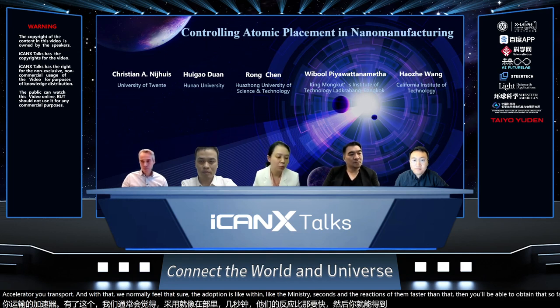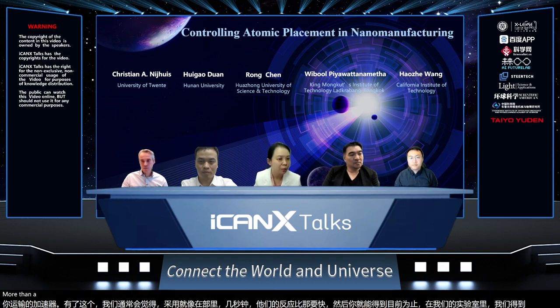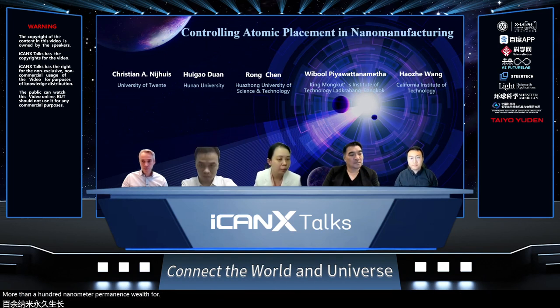In our lab, we obtain more than 100 nanometers per minute growth for the ALD process. That's pretty high, and that's the way we're trying to push to the limit. At the same time, in order to keep them uniform, you need to make sure you don't have CVD components, and you have enough time to let the byproduct go away, etc.